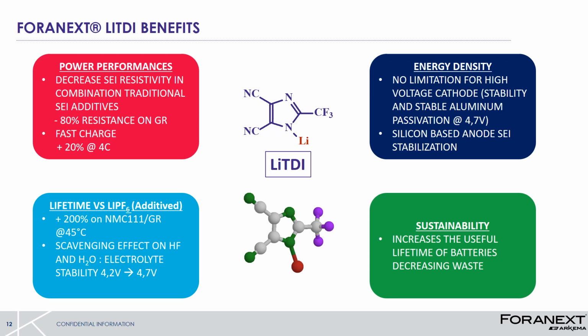The LiTDI is useful also to stabilize the SEI with a silicon-based anode. For the lifetime, the LiTDI is able to stabilize LiPF6-based electrolyte, especially at high temperature, thanks to its scavenging effect on HF, water, and Lewis acid. In terms of sustainability, LiTDI increases the useful lifetime of batteries and decreases the waste.